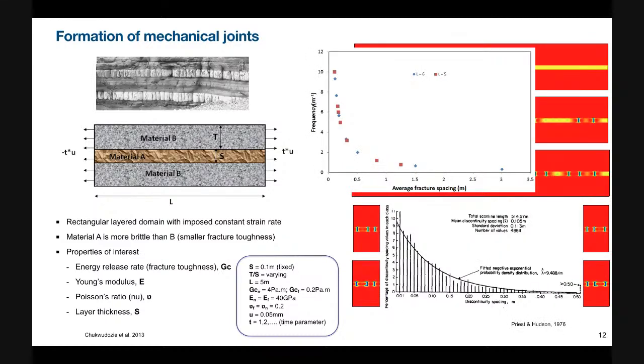And then the existing fractures, this layer debonding, starts forming some shear fractures and then some layer debonding. So the mode of fracture changes from mode 1 to mode 2 here. And we can also count the number of fractures in the layer. We plotted the frequency against average fracture spacing, and it seems to follow a negative exponential distribution function, and that seems to agree with field observation.